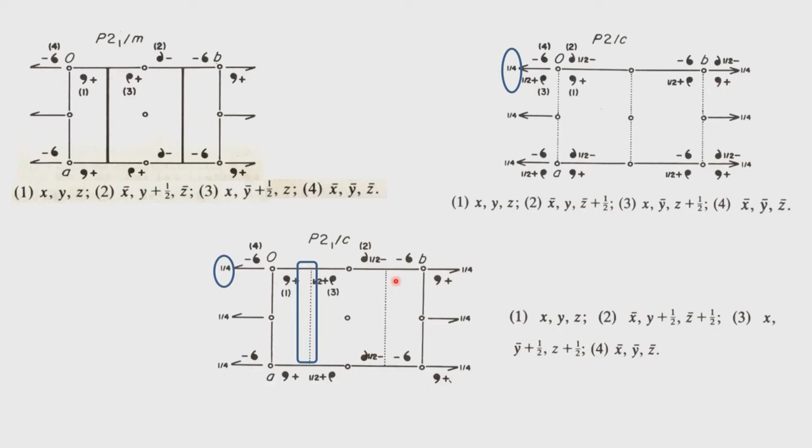So in a nutshell, what we will see now is that we have discussed the primitive lattices associated with the 2/m symmetry. We now have to worry about the presence of the C-centered lattices. So if we now think of a C-centered lattice, we should have a space group C21/m, a space group C21/c, and also C2/c. We have already seen in the earlier class that C2 and C21 are one and the same. It is just a question of shifting the origin by 1/4,